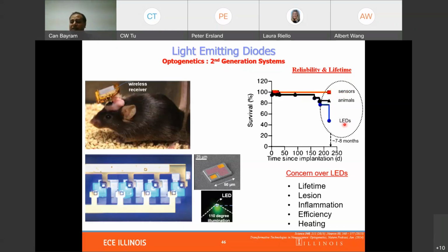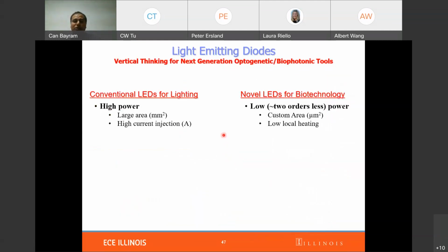So typically there is an interest in creating these thin film conformal, much more robust bio LEDs so that we can reduce the concern over lifetime use, lesion, and these kinds of problems. And again, when we are talking about biostructures, heating is important, so we want to make sure that we do not increase the temperature of the biosystem at all, if possible. So looking into conventional LEDs with respect to novel LEDs, the conventional LEDs are typically focused on the more high power range, whereas novel LEDs really require much less power. But the focus is more on the custom area and local heating.